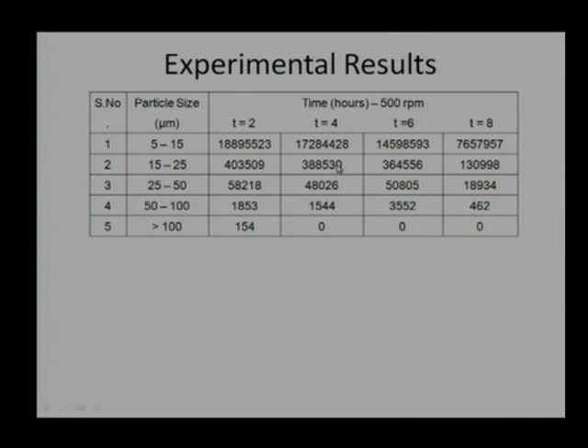And of course, before that, we tried to find out the particle size, what is the range of particle size, to diagnose whether the particles are of minor size, under a mild wear domain or a severe wear domain. And interestingly, we find too many particles for the size between 5 to 15 micron. Interesting thing, this number of particles is continuously decreasing with time. That means it is going for the betterment, it is going for convergence. Continuously the number of particles is decreasing. Coming to 15 to 25 micron, again the number of particles is continuously decreasing. So, that is a favorable situation.